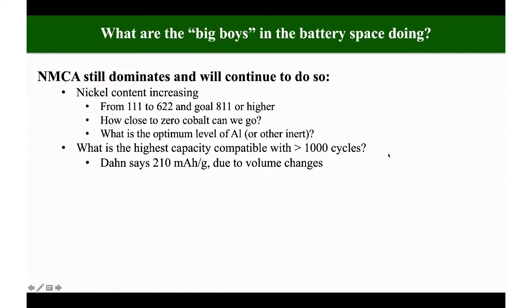And a big question that's been raised in the last year is, what is the highest capacity compatible with getting more than 1,000 cycles with these layered oxides? Jeff Dahn says it's 210 milliampere hours per gram. This is because above that, the volume contracts a lot, so the material tends to crack. If it cracks, then you get new surface that reacts with the electrolyte, and you lose the electrolyte, and your capacity retention is very poor.